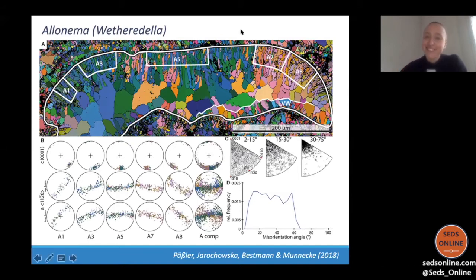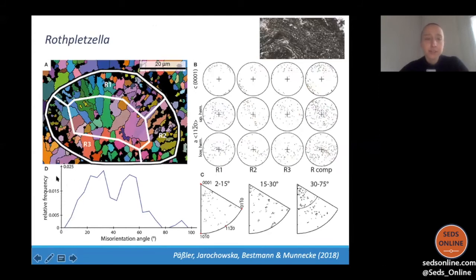And now this is maybe the trickiest part, because each misorientation is a mismatch between two grains. So if two grains are parallel, they will have a zero misorientation, but if they are misoriented, they can be misoriented along different axes. And so we can analyze the distribution of orientations of misorientation axes. And this is what we analyze here. These graphs are called inverse pole figures. And we see that misorientation axes that are very narrow are very common, whereas axes that go above 30 degrees are quite constrained. So in this case, we found it useful to constrain the crystallographic texture.